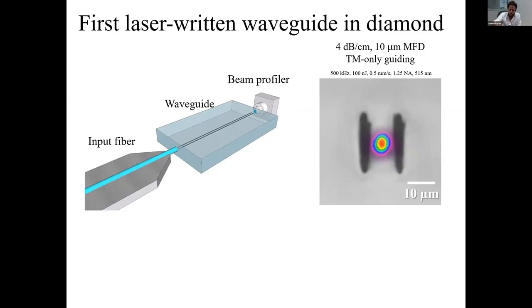One thing to note here is that it's quite elliptical due to the self-focusing within diamond. Even though we used an oil immersion lens, we had significant spherical aberration, my apologies, because of the high refractive index difference between the oil and the diamond, oil being around 1.5, diamond having a refractive index of 2.4. This causes quite an elliptical modification within the diamond.